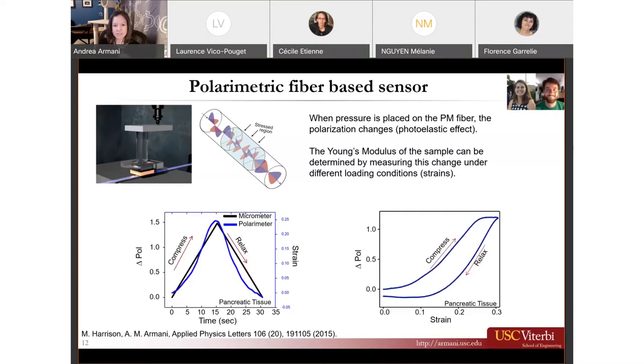And just as a couple of simple examples of how this looks in reality, this is a sample of pancreatic tissue taken from a pig. When we compress and relax, so when we apply a pressure and then remove the pressure, the actual force that we've applied and removed is that black line. That's the signal taken from the function generator. And the response that we measure, the polarization change, is the blue line.